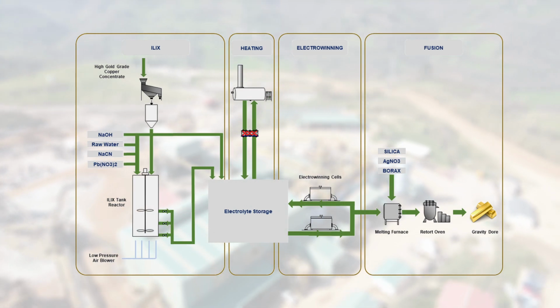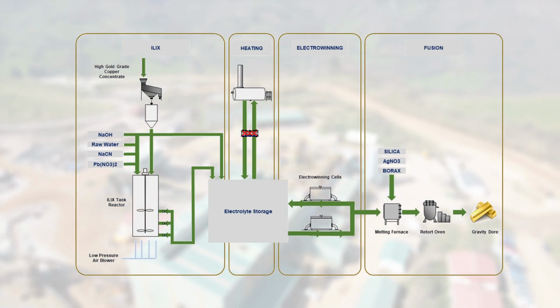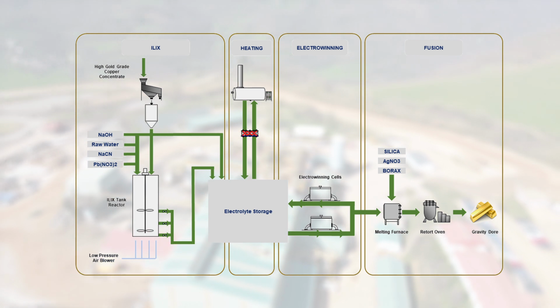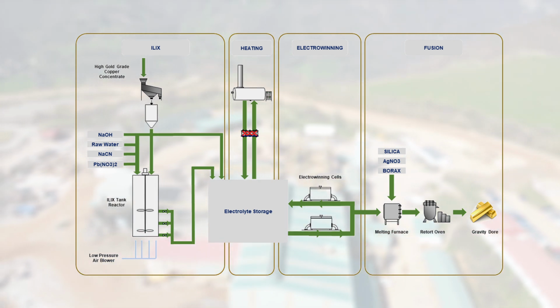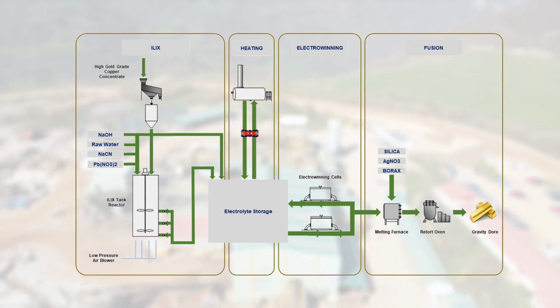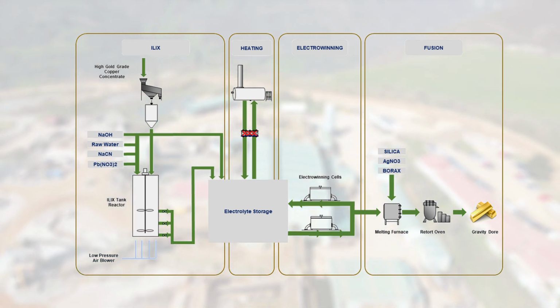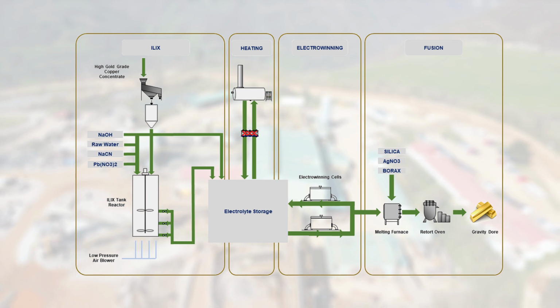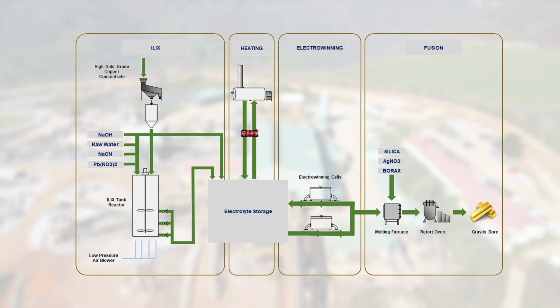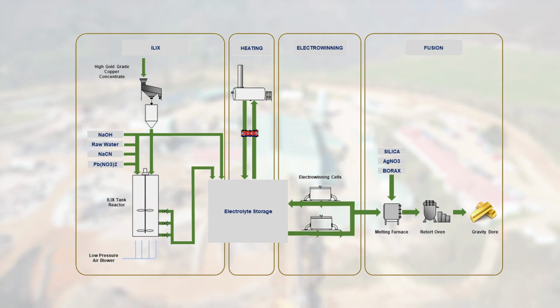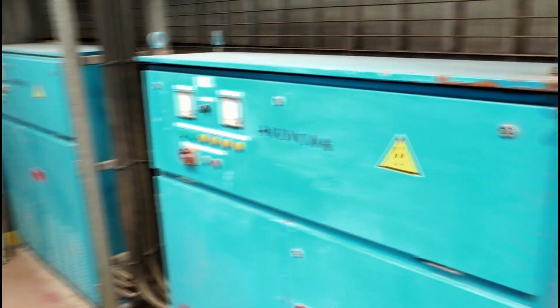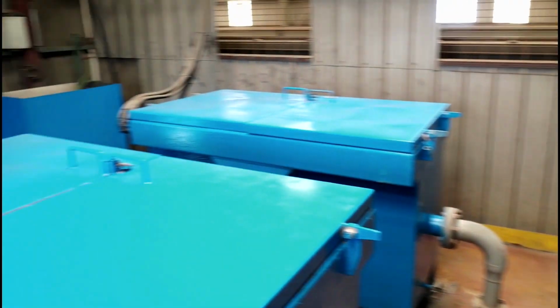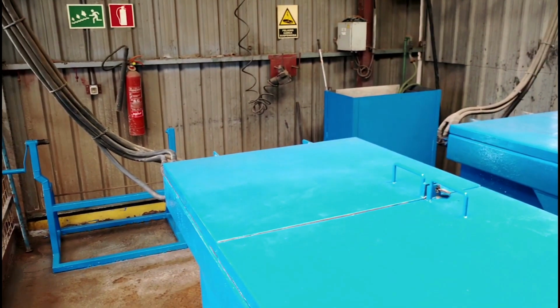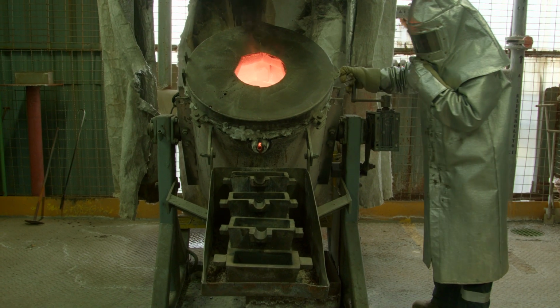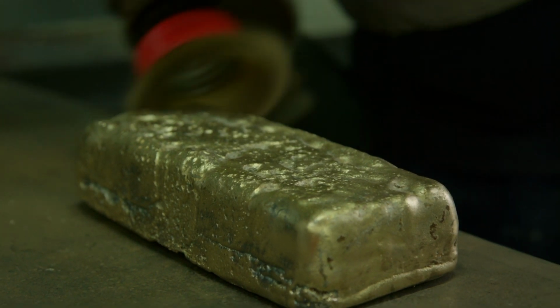The ILIX circuit consists of a reactor, an electrolyte tank, and two electrolyte cells. The high-grade gravimetric concentrates enter the reactor, to which a mixture of fresh water, caustic soda, and cyanide is added. The cyanide dissolves the gold present in these concentrates. The solution, when charged, is separated from the solid residue by decantation. The solid material returns to the ball mill, and the liquid is sent to electrolysis, where the gold is turned into solid state in the form of a slurry. This slurry is finally smelted to obtain the gravimetric bullion.